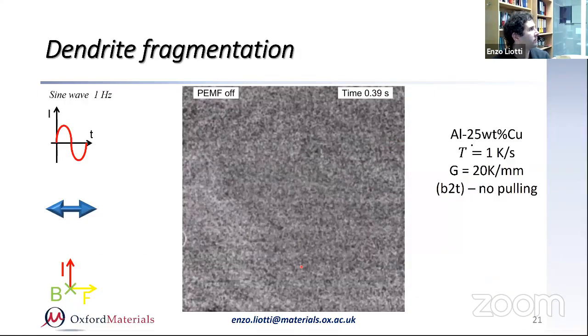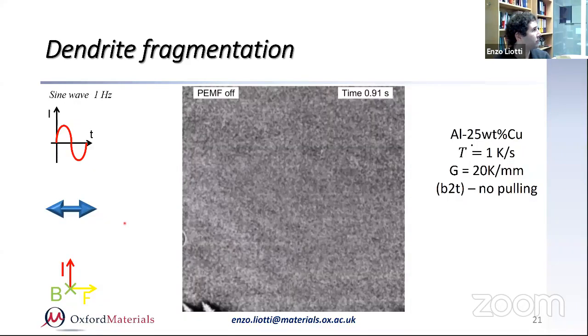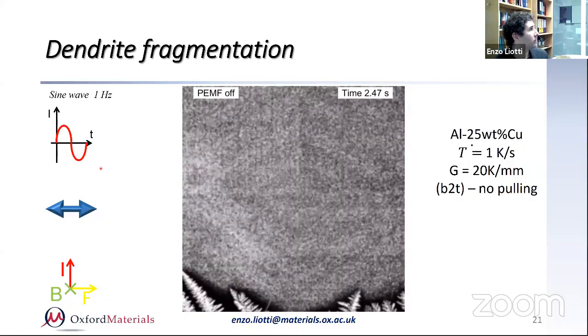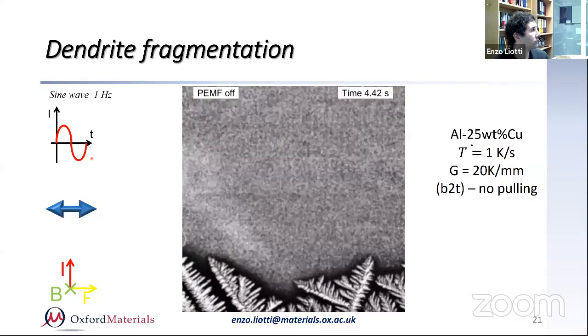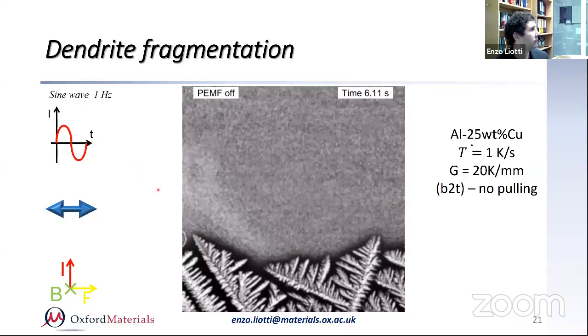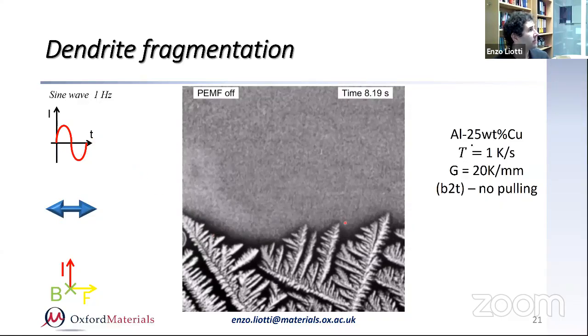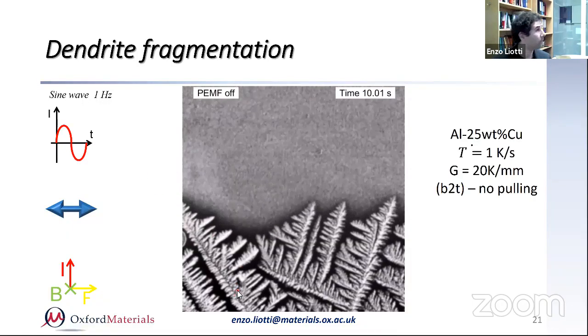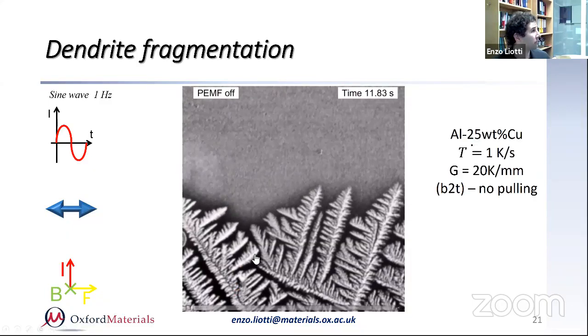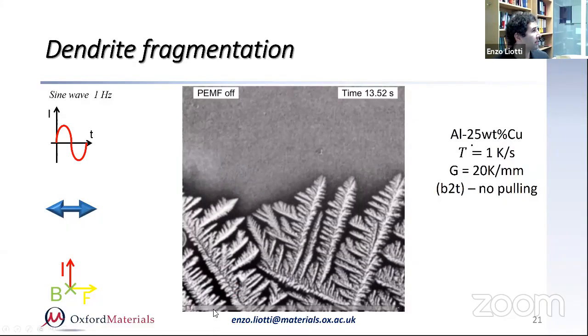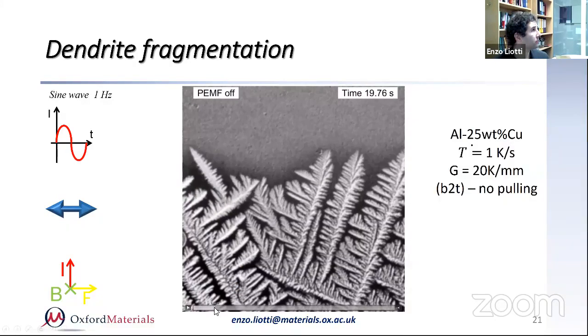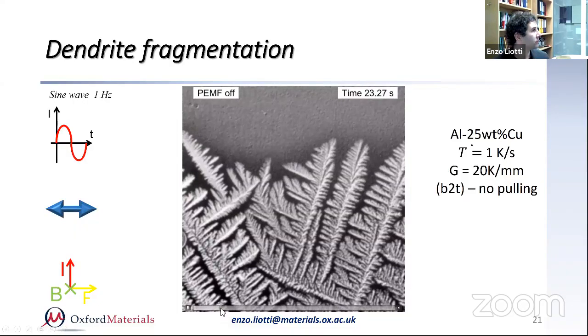This case instead is an oscillatory case. So what happened is the dendrites are growing, and here we are using a sine wave of 1 Hertz, which is positive and negative. So the liquid is steered left and right, and the dendritic array is growing. And if we go to around 30 seconds, the PEMF will be turned on, and you will start to see fragmentation taking place.